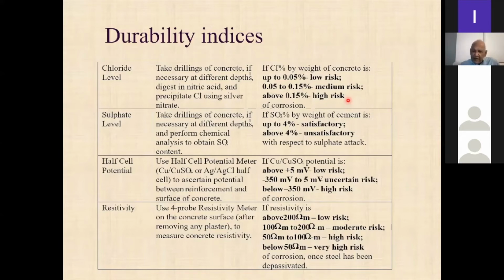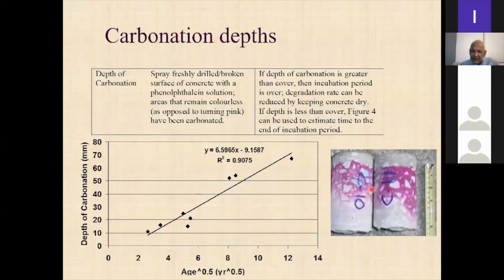you get carbonation depth. So what actually happens is that the areas that remain colorless in a phenolphthalein solution, those are the areas that have got carbonated, right? These are uncarbonated areas, right? So when you're doing this carbonation test also, you have to be careful. Typically, you should have this specimen horizontal like this, because if you have it vertical, then this red coloration of the phenolphthalein will run into this area as well, and you will not be able to get a good measurement.